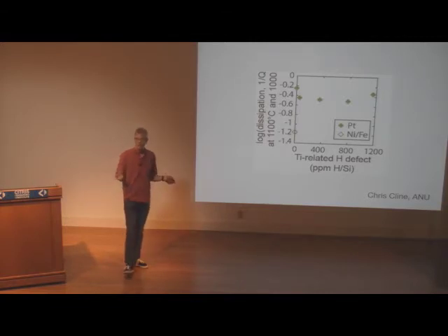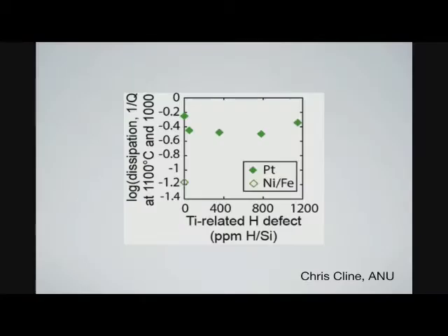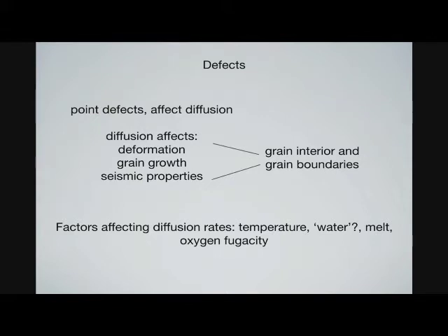What we do in large strain deformation experiments is we migrate dislocations, and so somehow for dislocation motion, the water content is important, but for this grain boundary sliding process, it seems like water content, presumably in the grain boundaries, is not important. So that's the summary essentially, and I take questions.